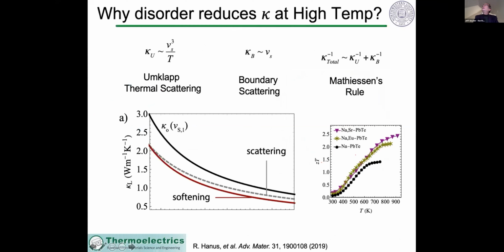Okay, so another point that we think is important is at high temperature, we see our thermal conductivities get very low, and this is again very important for thermoelectrics. Traditionally, we interpret this as a scattering effect, usually due to boundaries or impurities of some sort. But the nature of the thermal conductivity reduction seems to be fairly equal even at high temperatures, which is more akin to a softening type mechanism.